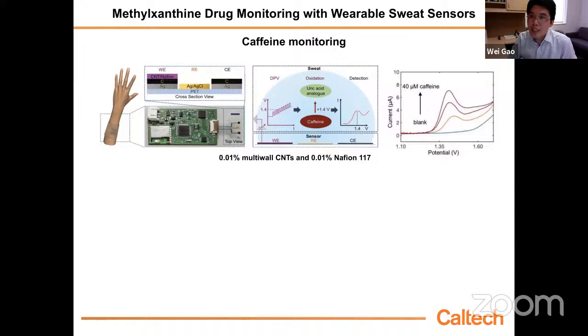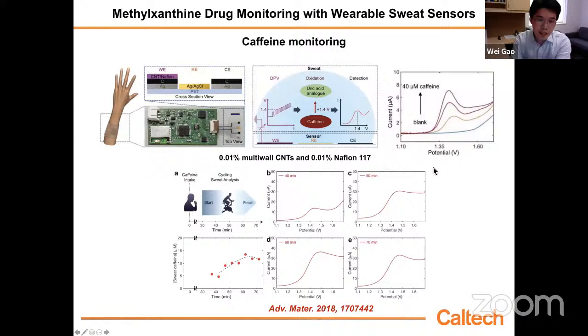And we developed this system based on printed electrodes, based on multiwall carbon nanotubes. And we used 0.01% Nafion coating to minimize the fouling to make sure the sensor can still last long and still have good performance. And we actually found that we can see caffeine level change after drinking coffee from our sensor. You can see the caffeine increase in the first hour, then start to decrease. And basically, we can study the entire metabolic process of caffeine using our wearable sensor.